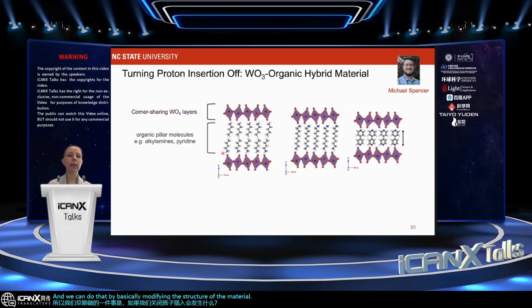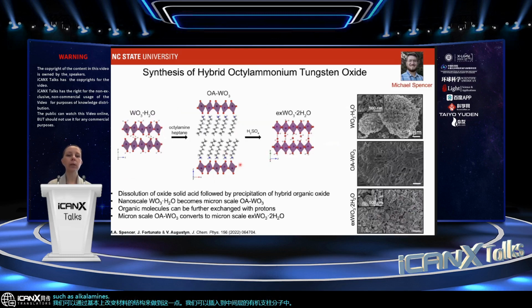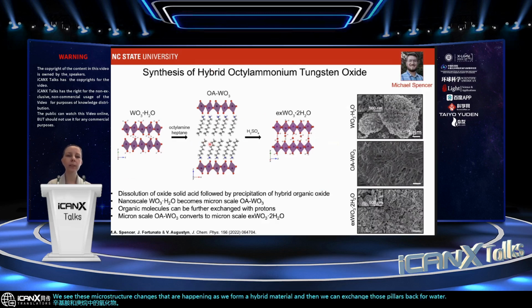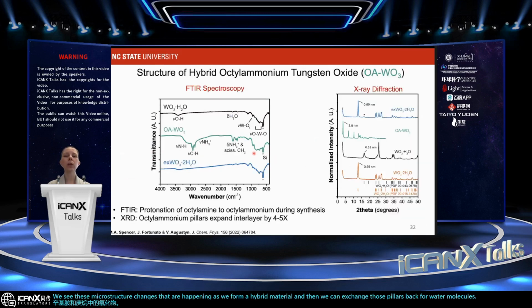We can intercalate into the interlayer organic pillar molecules, such as alkylamines. Well, they're actually alkylammoniums when they're in the interlayer. This is how we do it. It's a dissolution followed by reprecipitation process of the initial oxide in octylamines and heptanes. We see these microstructure changes that are happening as we form a hybrid material, and then we can exchange those pillars back for water molecules. So this process is reversible afterwards.